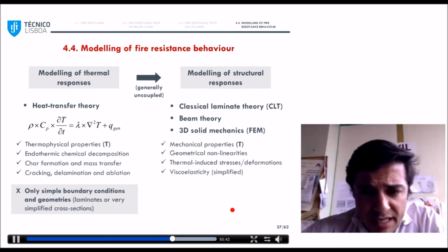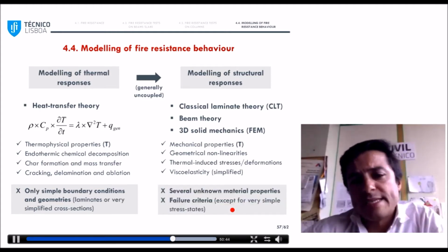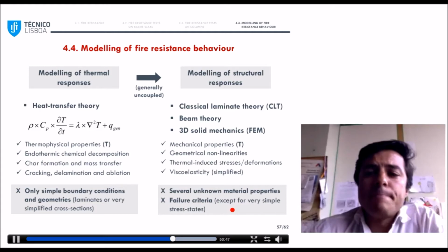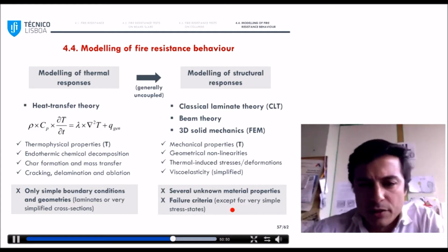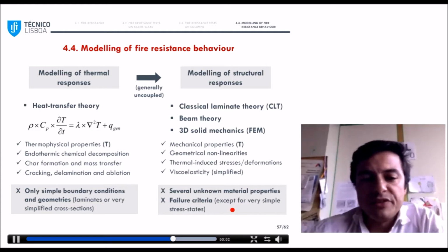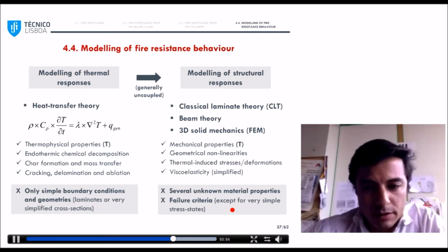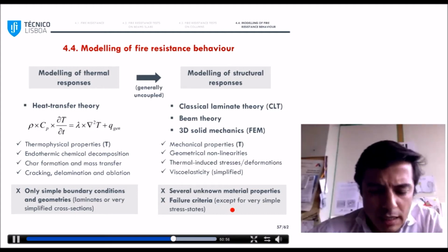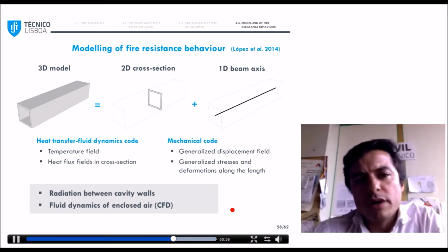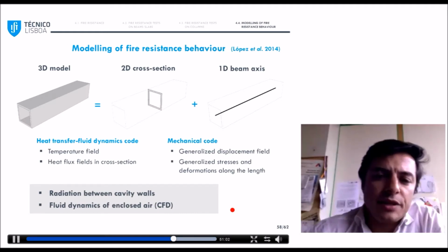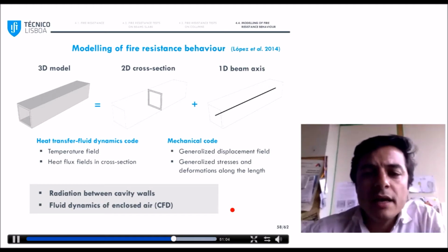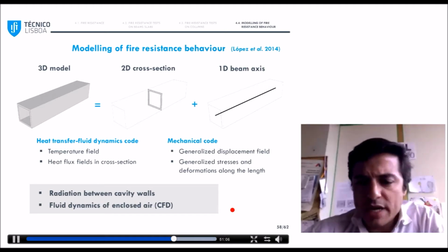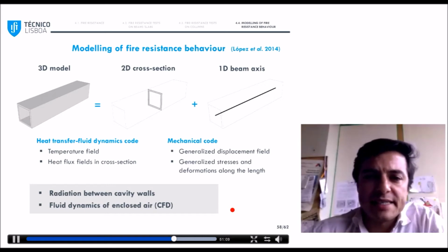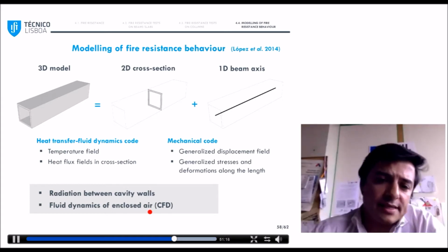In this case, I would point out as main limitations the uncertainty about several material properties which are not yet determined in the literature, and the applicable failure criteria. Let me show you work that was done at IST within the thesis of Cristina Lopez. In this work, we tried to simulate the fire resistance tests of GFRP beams and columns. We followed a two-step procedure, as in previous works.